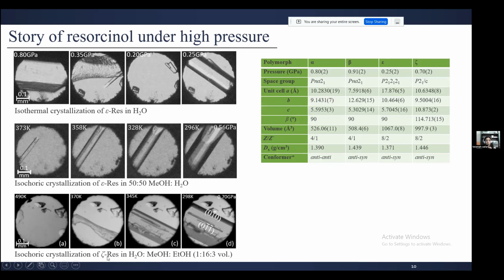But in this step, we were looking for the reasons, because I also tried this experiment at least 7 times each to be sure the epsilon is not an ambient condition phase. But what was the reason that they got it and I couldn't get this form?